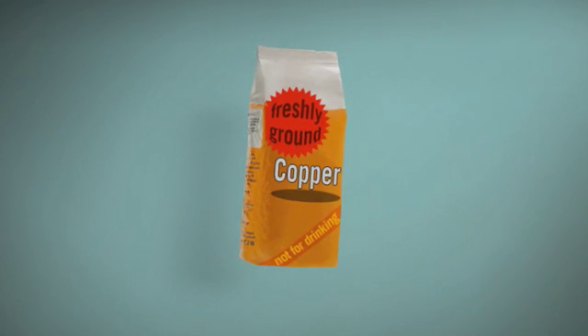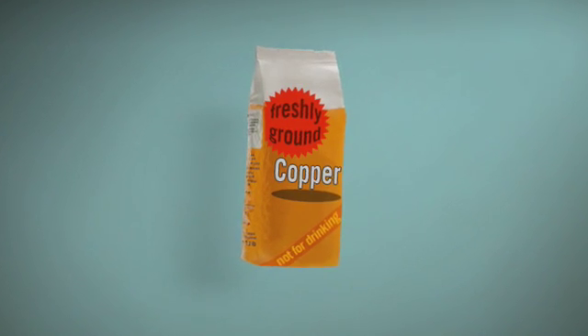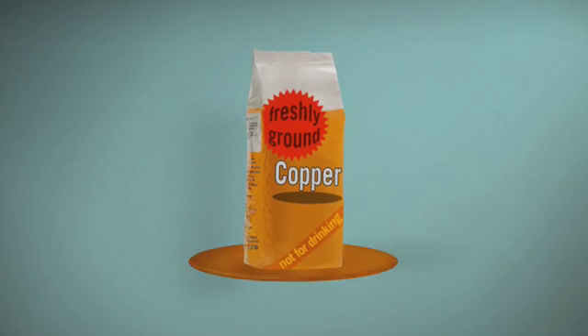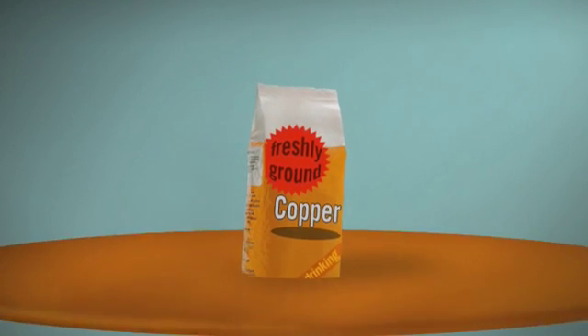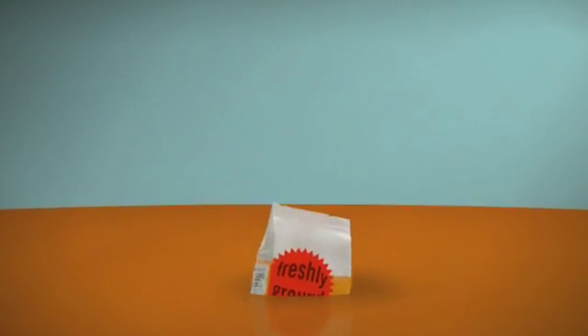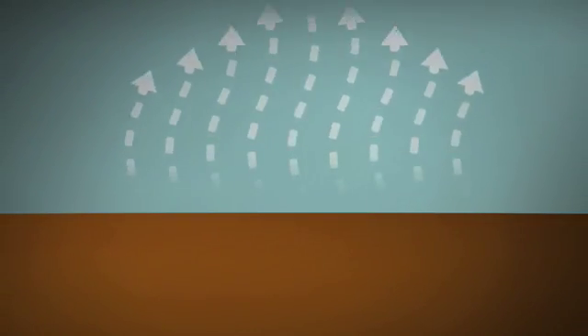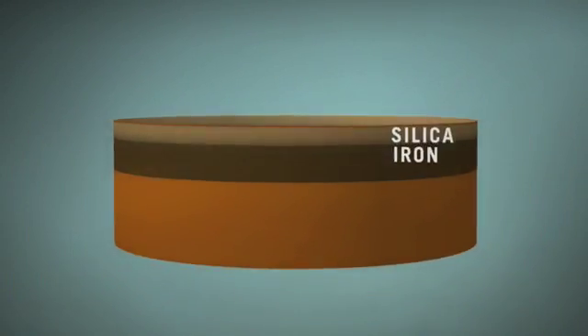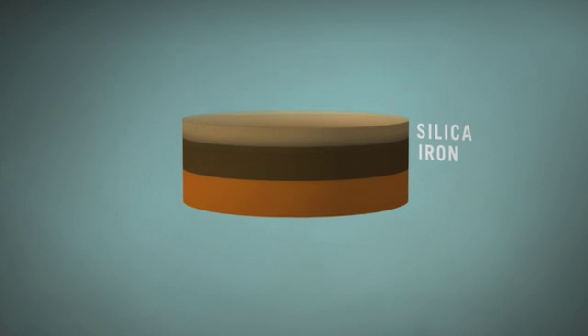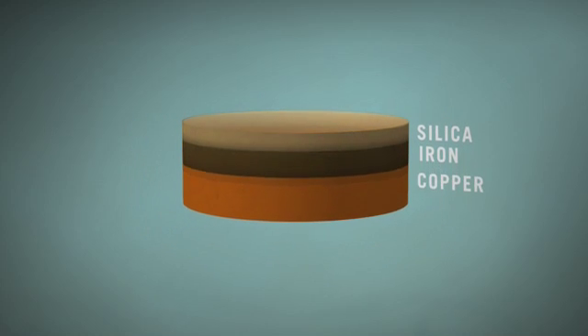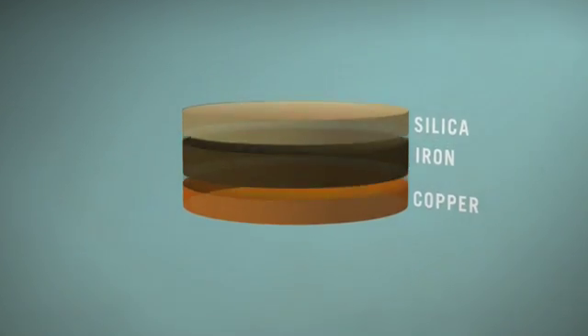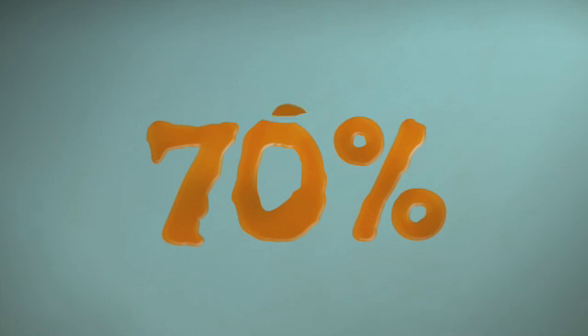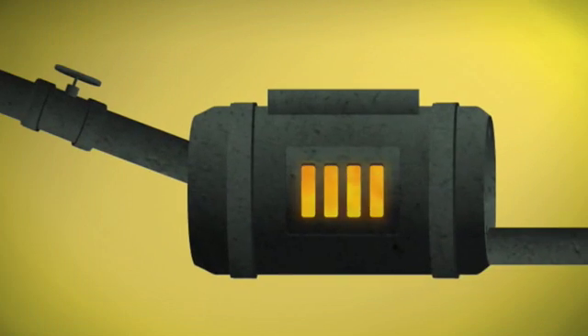This powder goes into a large, very hot flash furnace, which causes the dried concentrate to melt and turn into a molten metal called matte copper. During this process, sulfur gases burn off and are then captured and cleaned. A combination of iron and silica rises to the top and the heavier copper matte sinks to the bottom. This matte, which is now about 70% pure copper, is collected, cooled, and sent through yet another series of furnaces.